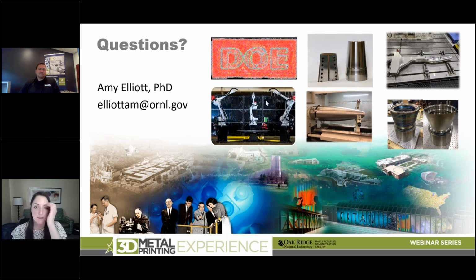Yeah, so like I said, the machining time, the time it takes to swap from like an additive part to a subtractive machine, that time is completely eliminated, obviously. And then also getting into like deep cavities. So like for the hexagon part that was shown, that's actually a pretty deep pocket to machine. And that would take a special tool, and you'd have to go at certain speeds to get to that depth. But if you're just machining an inch of that at a time, it becomes much faster, much easier.